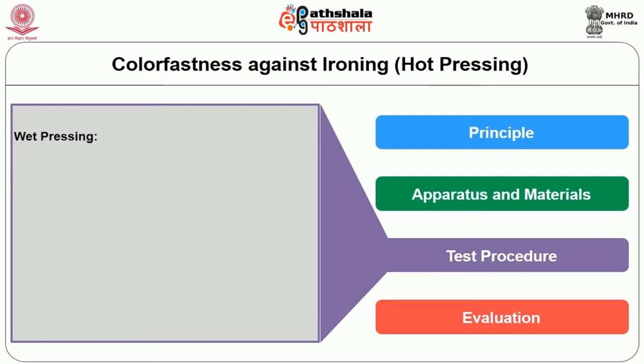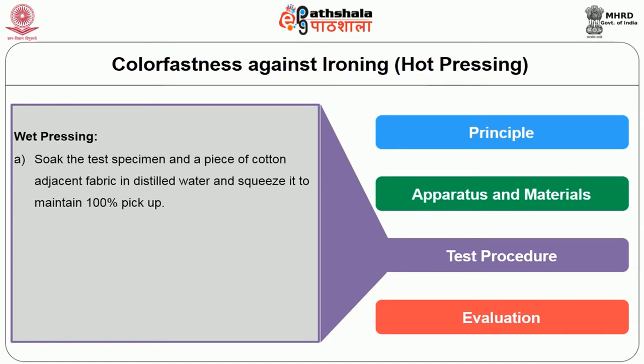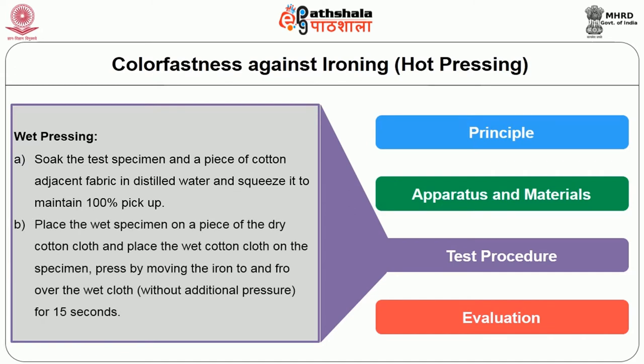Last one is wet pressing. Here, soak the test specimen and a piece of adjacent cotton fabric in distilled water and again squeeze to make 100% pickup. Place the wet specimen on a piece of dry cotton fabric and place the wet cotton fabric on the specimen. Press by moving the iron to and fro over the wet cloth without any additional pressure for the same 15 seconds. Evaluation is done numerically.